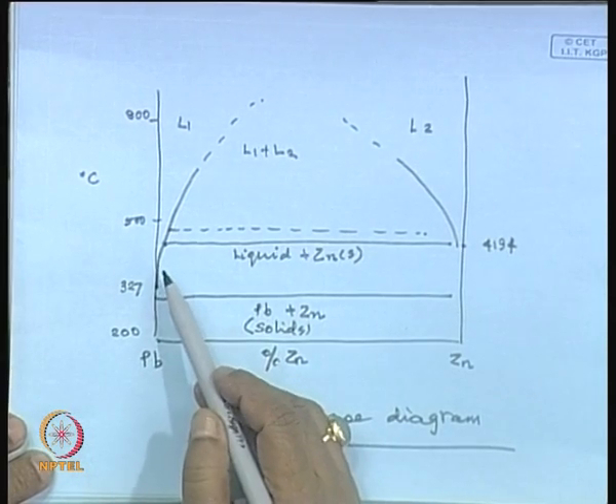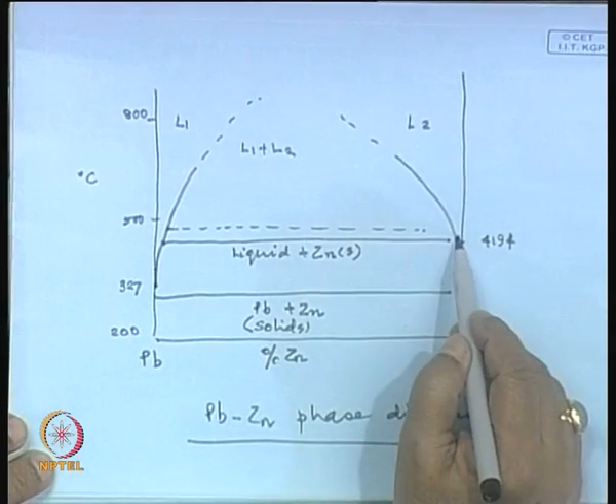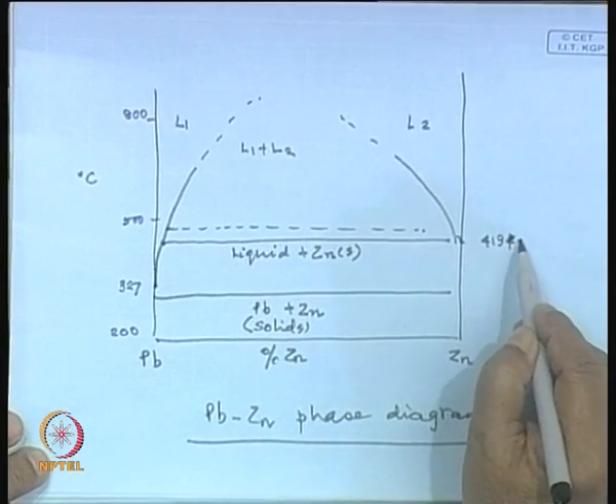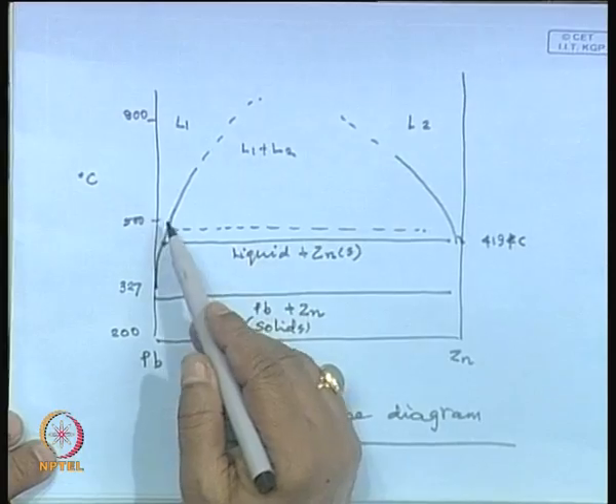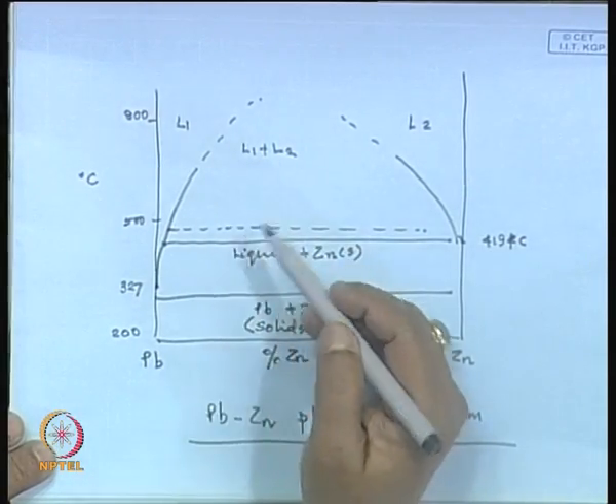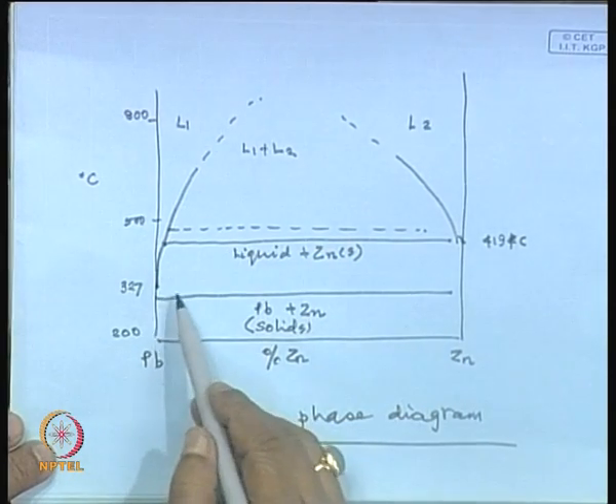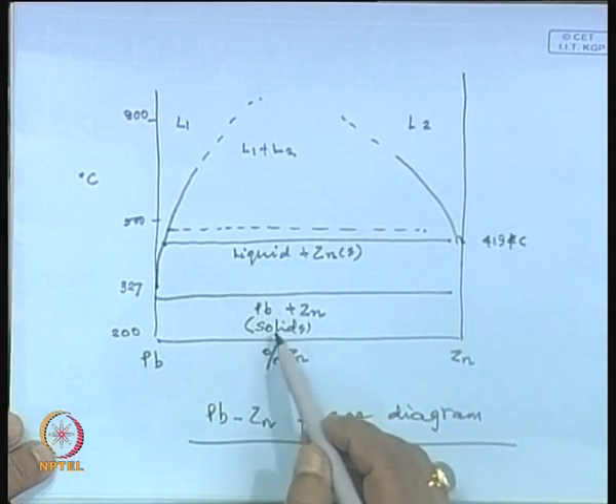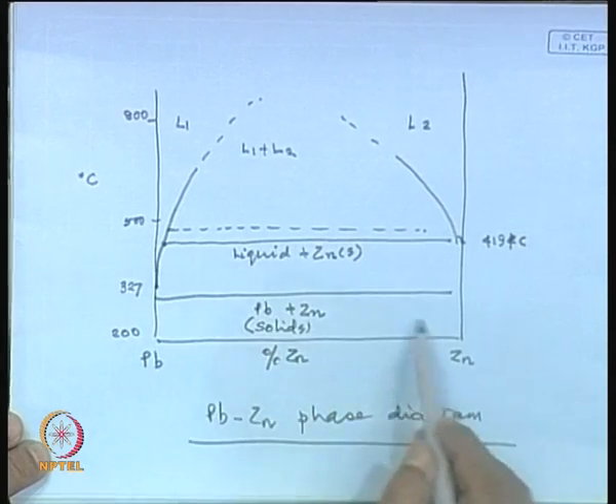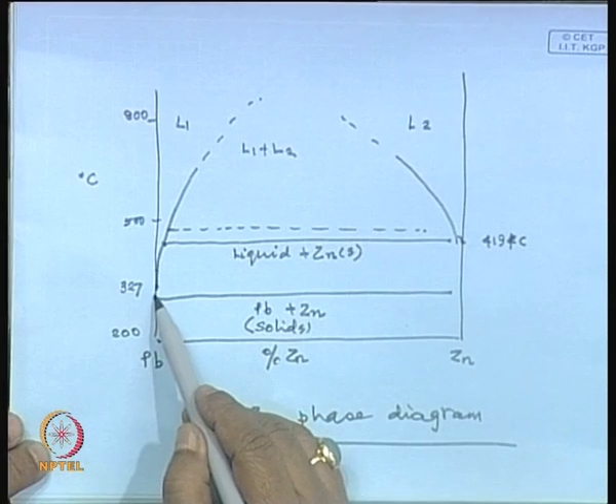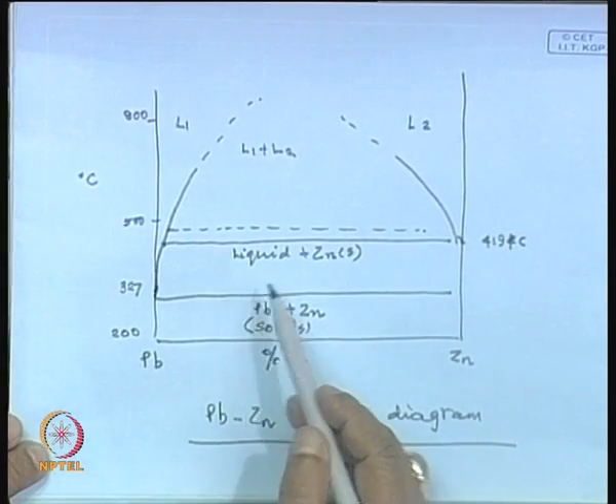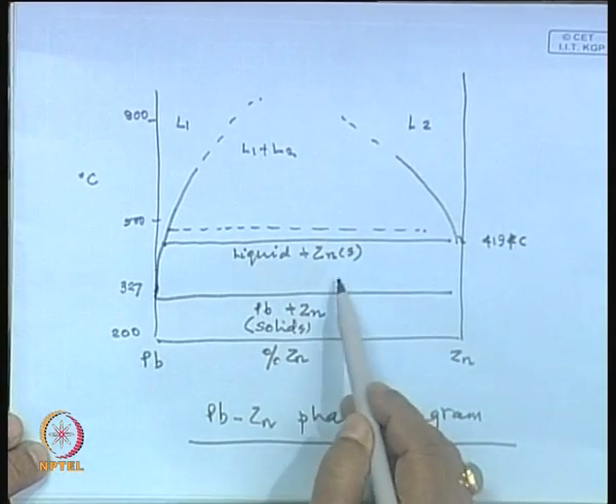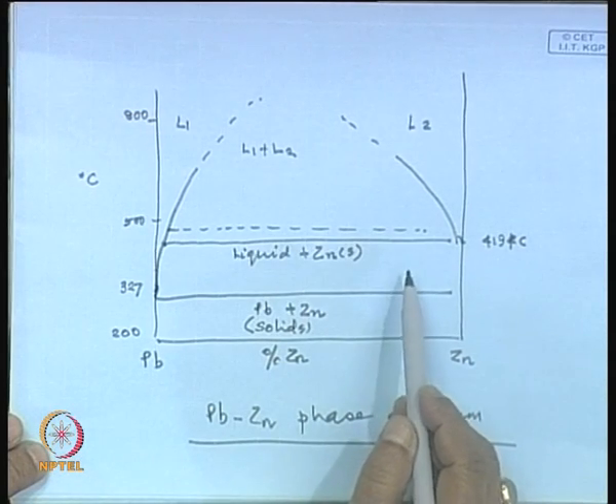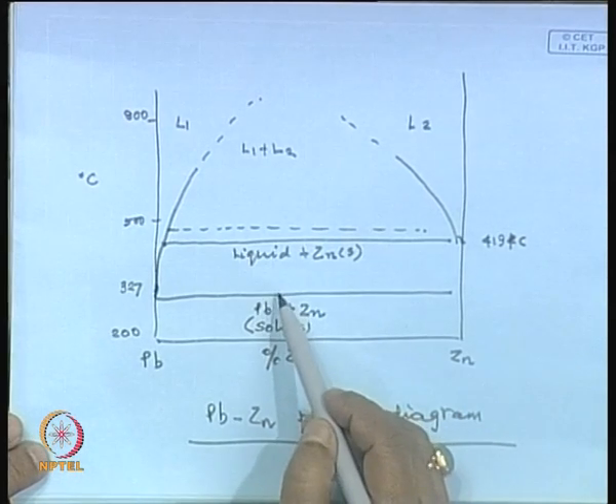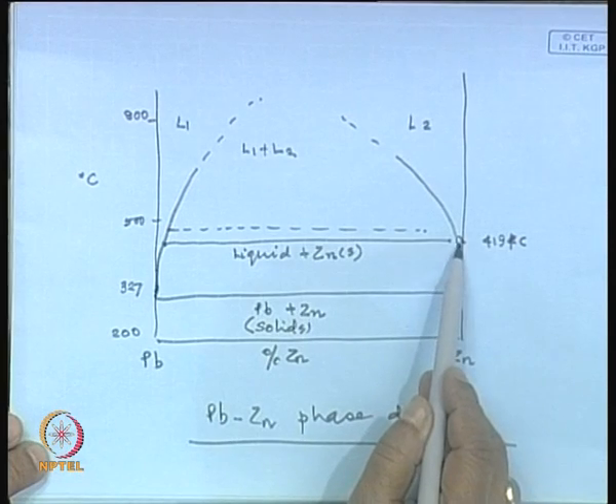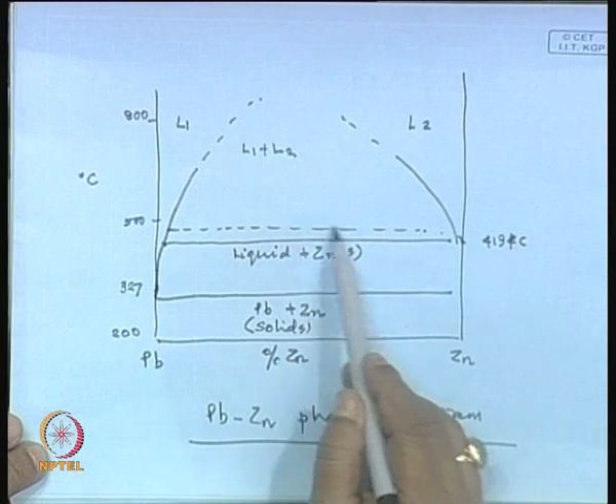Lead has a melting point of 327 degrees, zinc has a melting point of 419. If you go to these temperatures, two liquids separate out. If you are at a temperature below 327 degrees, then you have lead and zinc in a solid solution. If we exceed 327 degrees, then lead will melt out. So, here you will have liquid lead and zinc. Zinc will be solid, lead will separate out as a liquid. If we go beyond 419, then we begin to get two liquids.